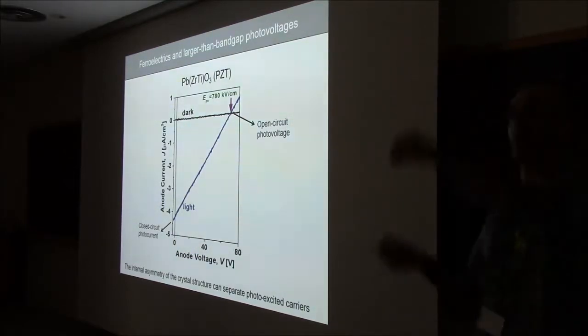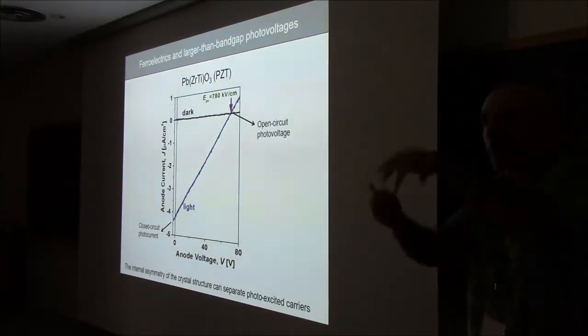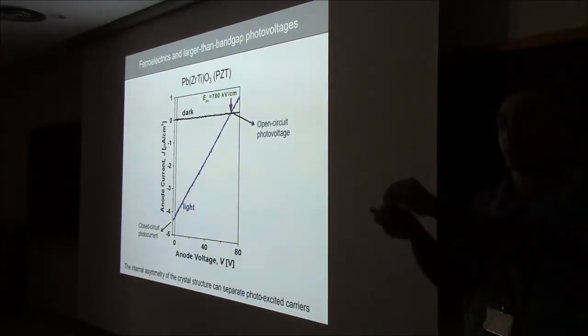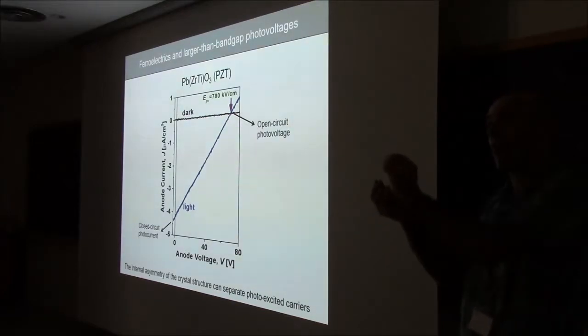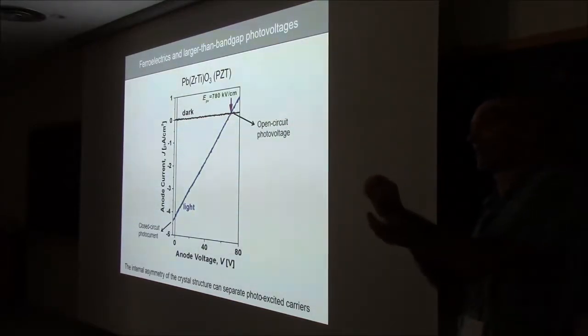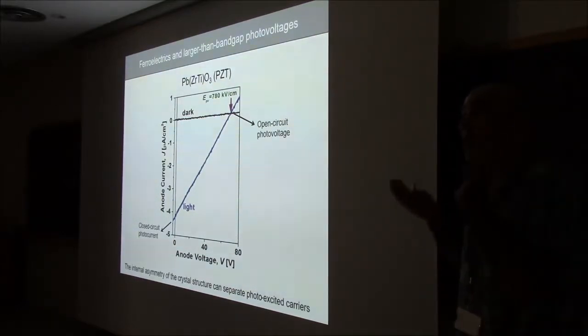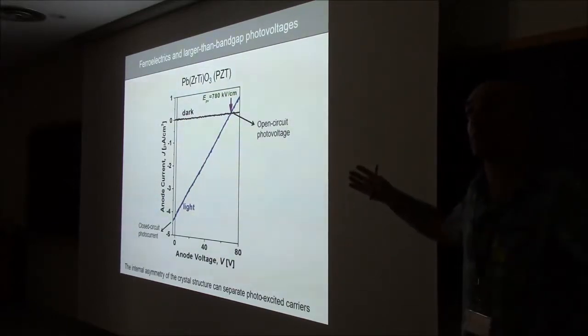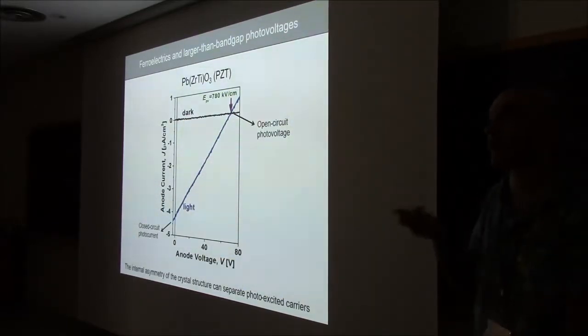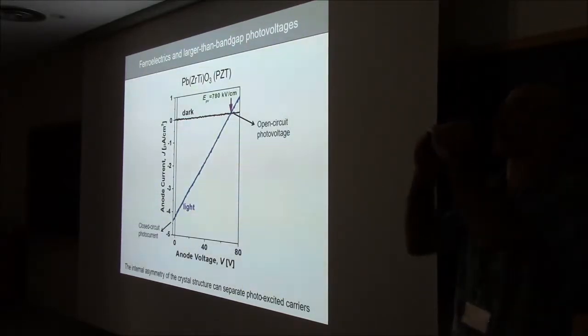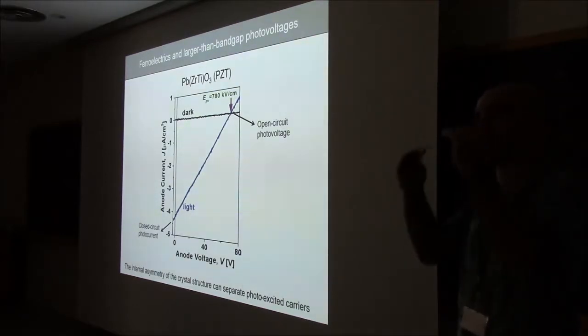Okay, that aside, once you shine light, if the light gets absorbed, you can create an electron-hole pair. Normally, an electron-hole pair will recombine more or less instantly, or on average, it will recombine wherever it's been created. But because the unit cell of ferroelectrics is asymmetric, electrons have a tendency to go one way, and the holes have a tendency to go the opposite way. Okay, so you can separate the charge just by virtue of the fact that it has been created inside an asymmetric lattice. This is called the bulk photovoltaic effect. It's a bulk effect. It does not depend on an interface junction between two semiconductors. Okay? You get it just for free from the fact that you have a lattice that is asymmetric.